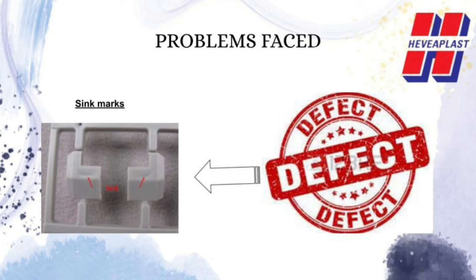The second defect is sink marks. Sink marks are small craters or depressions that develop in thicker areas of the injection molded prototype. When shrinkage occurs in the inner portion of the finished product, the effect is somewhat similar to sinkholes in topography, but caused by shrinkage rather than erosion. Sink marks are often caused when the cooling time or the cooling mechanism is insufficient for the plastic to fully cool and cure while in the mold.